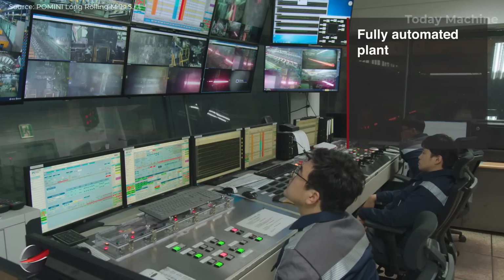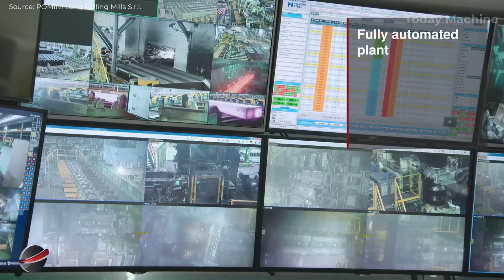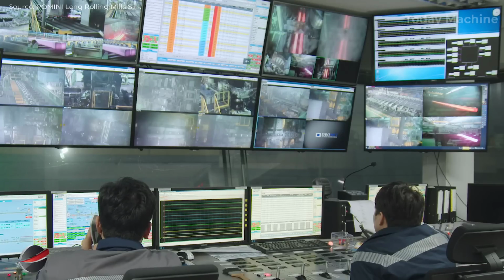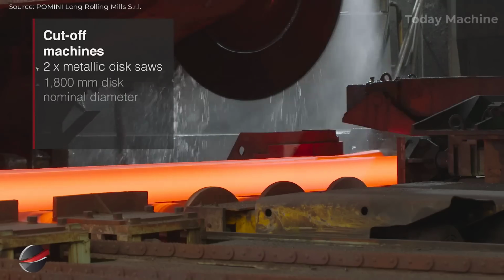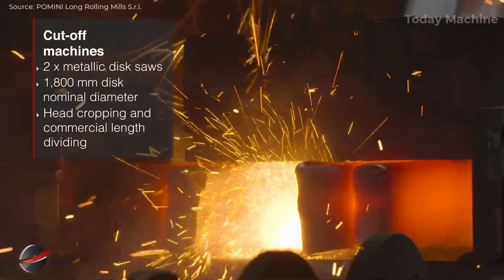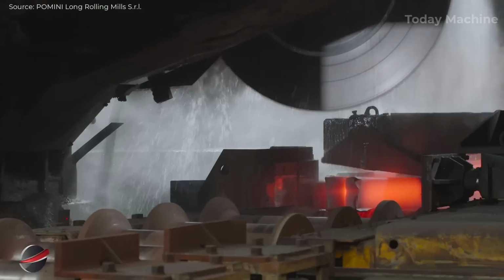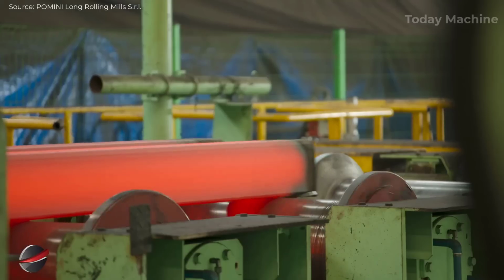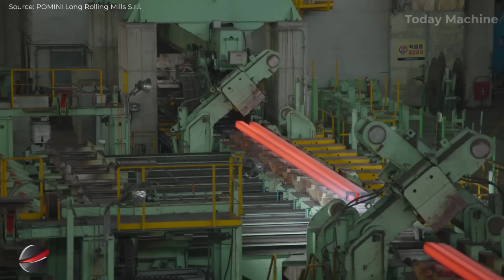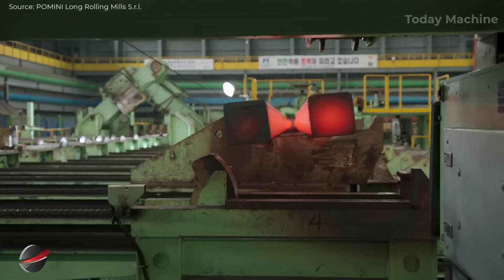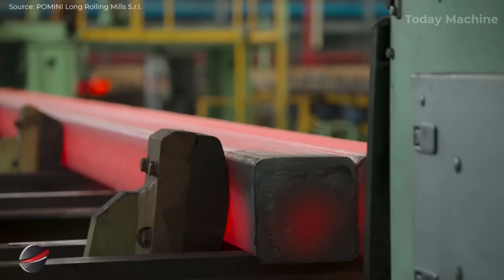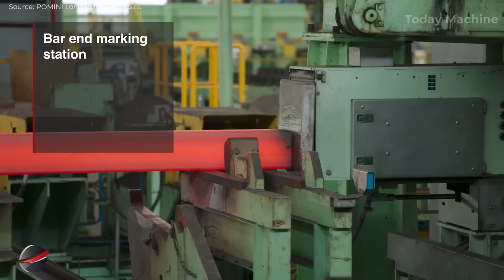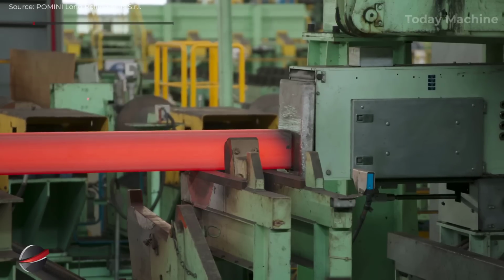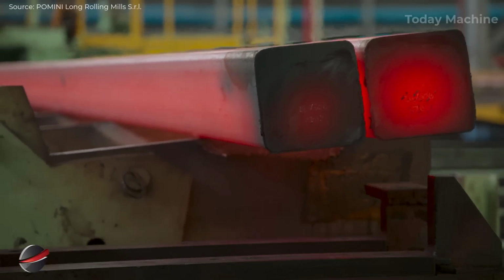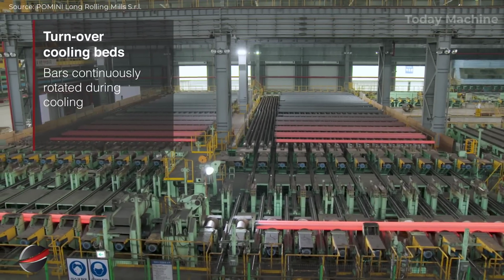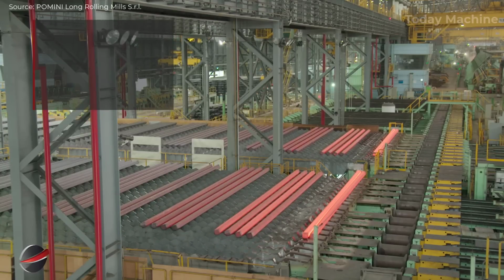Once the bars pass through the finishing and sizing stages, they move along the exit roller table and into layer forming systems. The plant is fully automated, handling the final stages of the process, including cutting, bundling, and marking the bars. Cut-off machines equipped with metallic disc saws, 1,800 millimeters in diameter, are used to crop the head and divide the bars into commercial lengths. The bars are then cooled on turnover cooling beds, where they are continuously rotated to ensure uniform cooling.